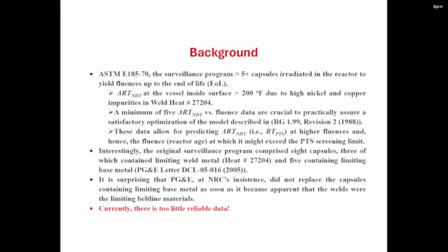As background, ASTM E185-70 stipulates 5+ capsules irradiated up to the end of life. And the reason for that is that the shift in the reference temperature was predicted to be more than 200 degrees Fahrenheit due to high nickel and copper in weld 27204. That was forewarned by Westinghouse. A minimum of 5 RT-NDT versus fluence data points are crucial to practical optimization of the model on the equations of RG 1.99 Revision 2, 1988.